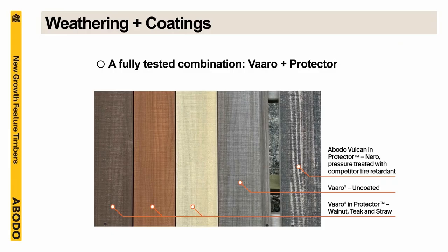And you can see uncoated, the timber weathers to a nice gunmetal grey, but you get very good coating performance on the timber, compared to on the far right is a competitor fire retardant which has been impregnated into our Vulcan product and then had the same coating applied. And as you can see, early failure of the coating is occurring. So we feel it's very important to test the combination of coating and base material to give customers confidence that in the long run they're not going to have any problems.